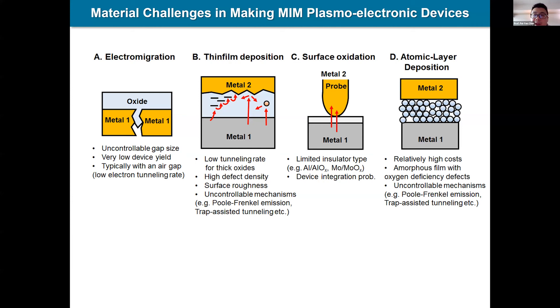There are several methods to produce the thin-film insulator. The first is electromigration — normally we have uncontrollable gap sizes and low device yield. The second type is thin-film deposition, with problems of high defect density and surface roughness. The third is surface oxidation — even though we have a desirable device, the insulator types are highly confined to specific types, for example aluminum oxide or molybdenum oxide. The last method is ALD for deposition; however, the cost is very high and sometimes there will be oxygen defects.